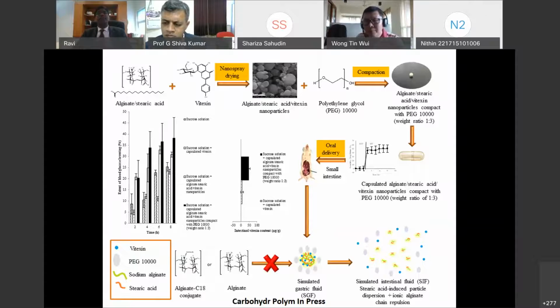In the intestinal regions, what happens exactly is that the PEG will be eroded with time in the intestinal fluid. Very importantly, the nanoparticles are constituted of alginate and stearic acid. Alginate is a polyanionic polymer, so in the intestinal fluid it will experience ionization, losing its proton. It will carry a negative charge, the alginate will repel each other, and the nanoparticles will be dispersed or fragmented. Stearic acid also has its role, whereby it will induce wicking. It can hit on the nanoparticle matrix and try to disaggregate it in the intestinal region. Hence, more vitexin will be released in the intestinal region for targeting the alpha-glucosidase. If we replace alginate stearic acid with alginate alone, there will be no favorable pharmacodynamic performance.